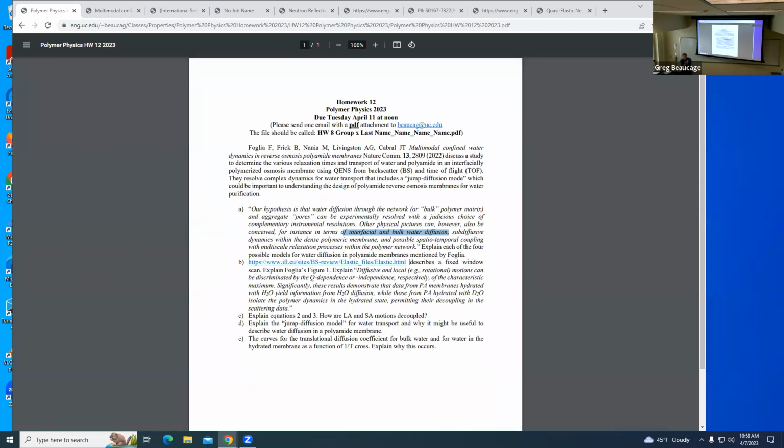And if the pore gets smaller than the molecular size, you have something like single-file transport, things that are kind of all wall. So then the transport gets really slow. Right, so you could talk about that interfacial versus bulk transport. That's one model that you could use. And then subdiffusive dynamics.